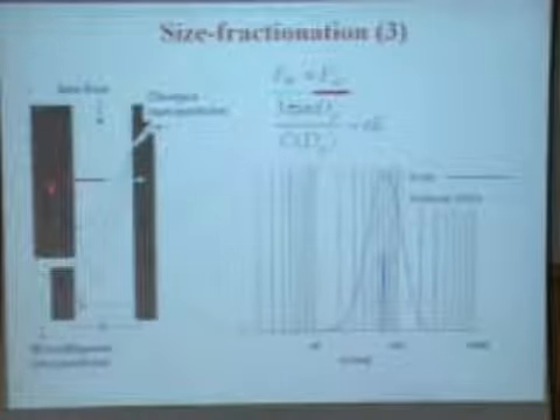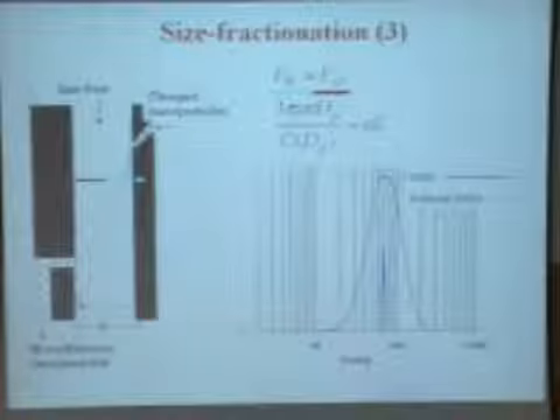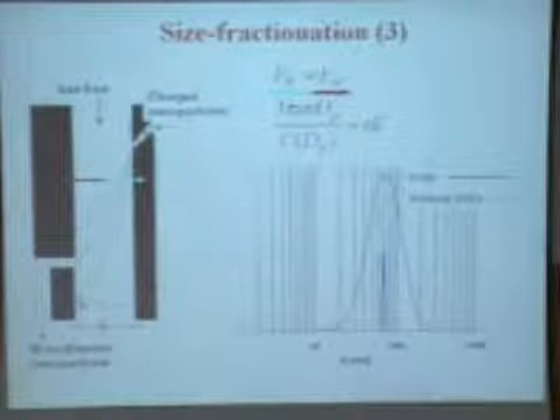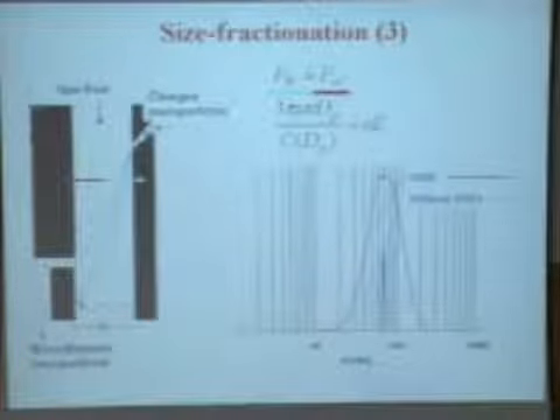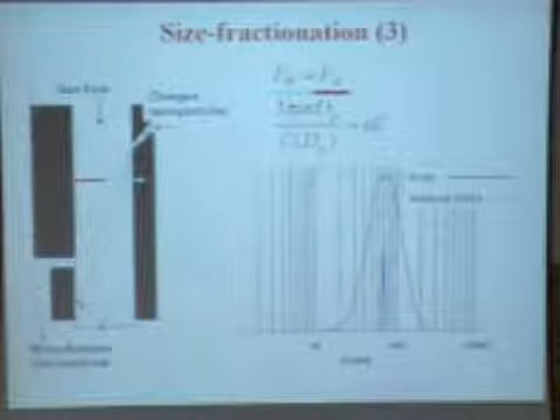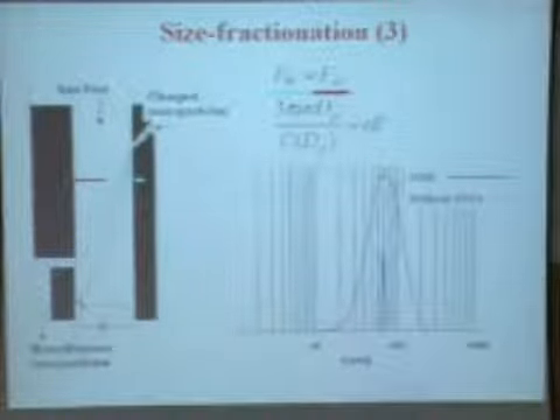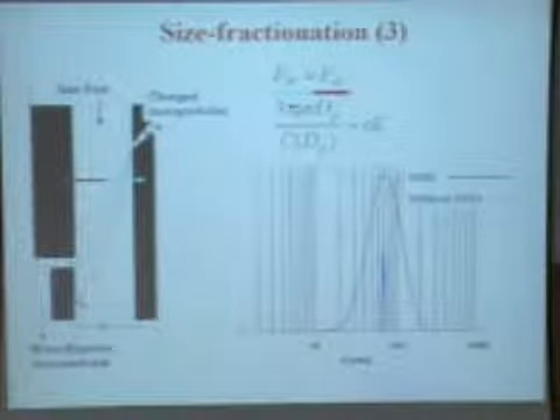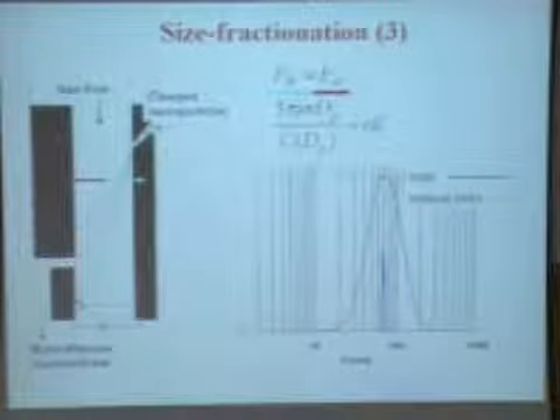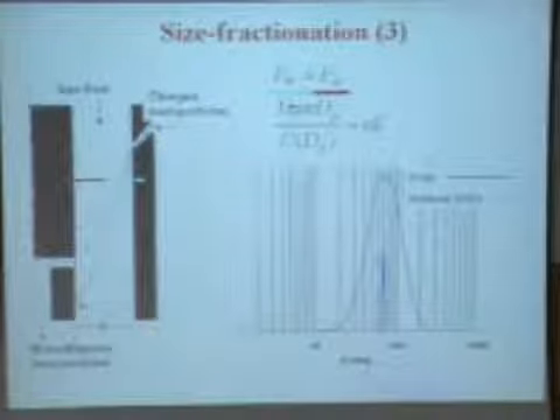And this is how the differential mobility analyzer works. You can see that, as I was mentioning, there is an inner electrode and there is an outer cylinder. You have an electric field between them. If you apply a positive voltage to this central electrode, then the negatively charged particles will go in this direction, and there will be two forces: one due to the electric field, because the charged particles will be attracted towards one direction, and there is a drag force, because as the particle gets accelerated, it is moving in the gas, which has a viscosity. The gas will retard their motion, and after some time they will get a terminal velocity. So they move depending upon their mobility in the gas, depending upon how much the gas retards their motion. Particles of a particular mobility enter this point, particles having smaller mobility are deposited on the substrate, particles having larger mobility go out in the exit, and you select particles of a particular size.